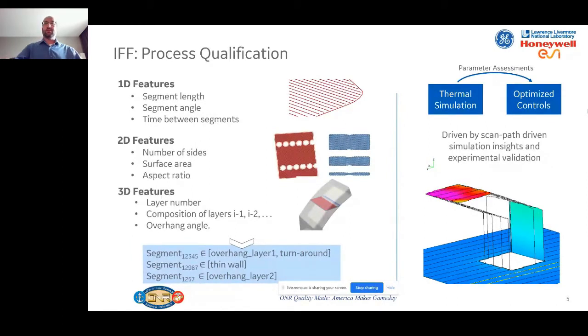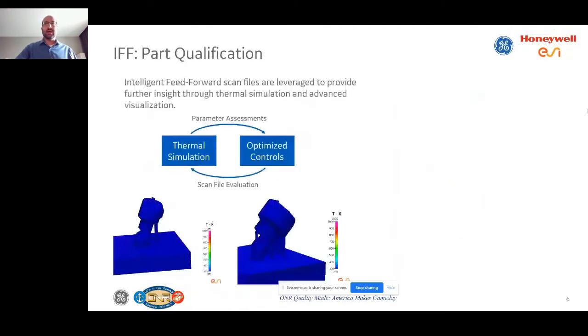But now furthermore, we can leverage this in the part qualification procedure. So we now have tailored control strategies around critical feature sets that we know we need to control better in the additive process. And we want to now leverage those in part qualification. So IFF itself, Intelligent Feed Forward, is meant to take those same feature sets that were developed under process qualification, now apply them to new geometries, identify similar feature sets when we go to a new type of design. But furthermore, we're able to close that loop between the controls and that thermal simulation, and now run that same thermal simulation strike by strike on a new geometry, tailored geometry that we're looking to do process qualification on. It can provide assessments around thermal buildup of regions, show ourselves optimal orientations of the process and an understanding of the impact of our tailored control strategies.